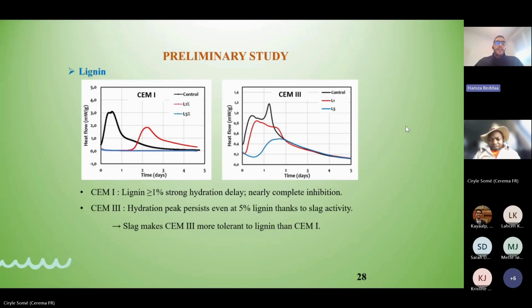So our preliminary study is about defining a realistic range of dosage of these two additives. To assess the impact of lignin and waste vegetable oils on the early hydration of cement, we performed an isothermal calorimetry test.